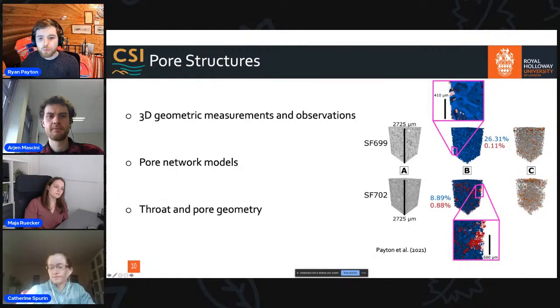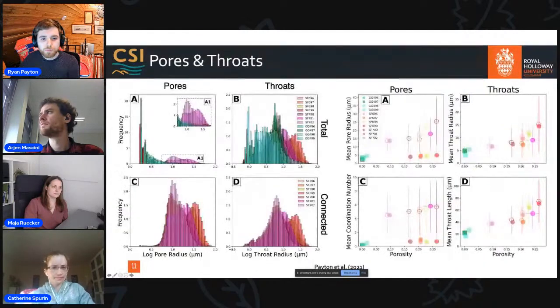However, in this sample, we can see that there is a greater proportion of disconnected porosity, but it's not really taking on that same form. It appears to be more intergranular. So this is an interesting observation to make. So we can then build a pore network model, which I'm sure many of you are familiar with, balls and sticks representing pores and throats.